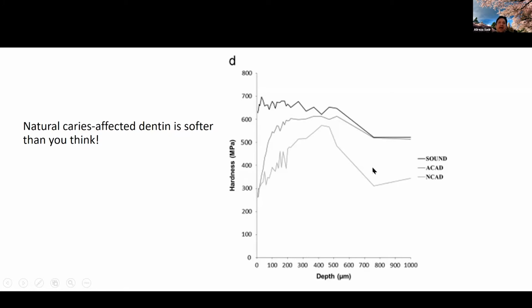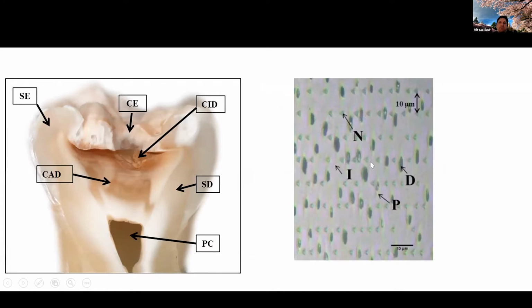So I think one message that I can give you from this particular study is do not expect to reach hard dentin, or even sometimes relatively hard dentin, as you're removing deep caries in a deep caries tooth, okay? So natural caries affected dentin is way softer based on the nano indentation. So if you measure the hardness within intertubular dentin, each of the indenters is about a micrometer or 2 micrometers in size, then we can see that it's pretty much soft.